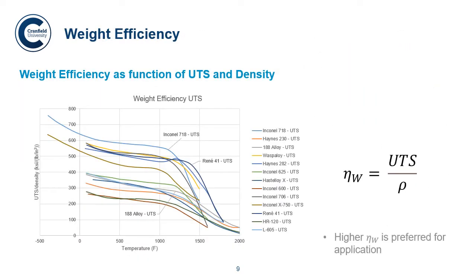So then we looked at weight efficiency. We define weight efficiency as a function of UTS and density. So a higher weight efficiency is preferred for the application. You see Inconel 718 again, it's coming out very good at sort of intermediate temperatures, and then we have Rene 41, which is getting good at the kind of high end, and then 188 again is coming out top at the real high end.